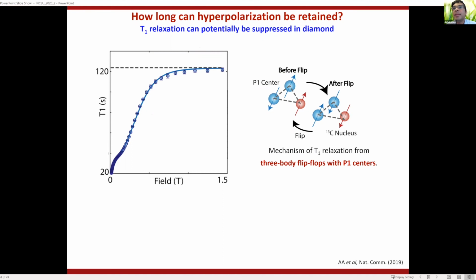But the main reason why they are not as useful as C13 in this case is because they are not so abundant. So every NV has an N14, but that's all. But the number of NVs is only a part per million in the lattice, between 1 part per million and 10 parts per million. But C13 is what makes up the lattice in the first place, and you can make diamond out of pure C13. So there are way more of these nuclei. So it's easier to see with NMR, and it's easier to manipulate. So that's basically the difference between them. Thank you.